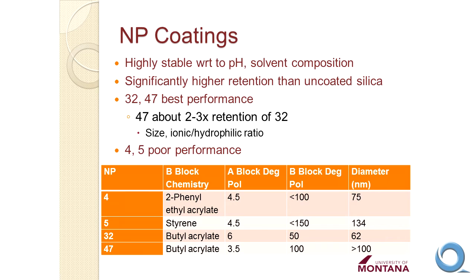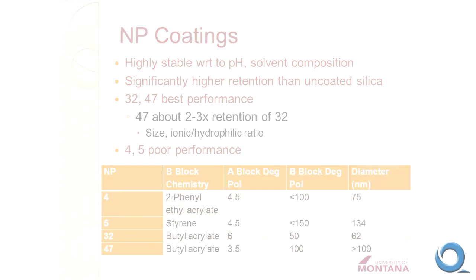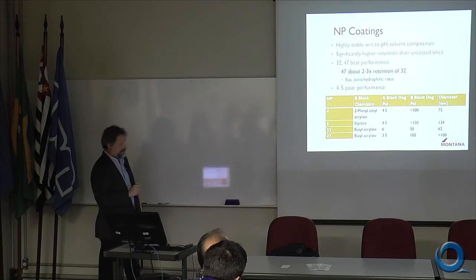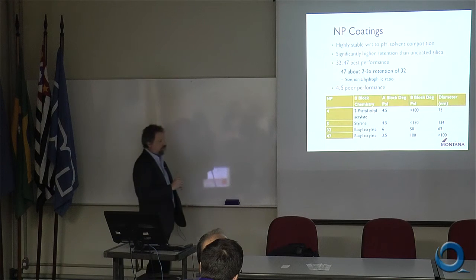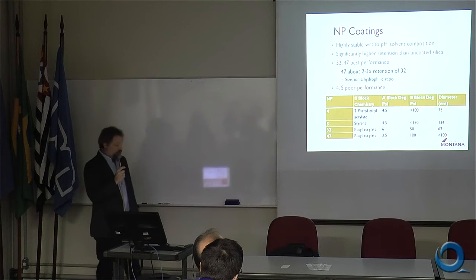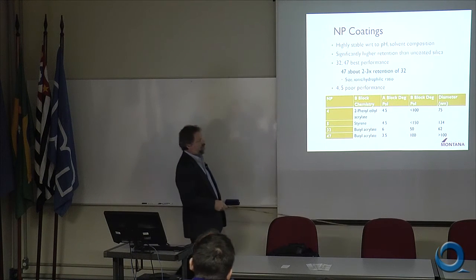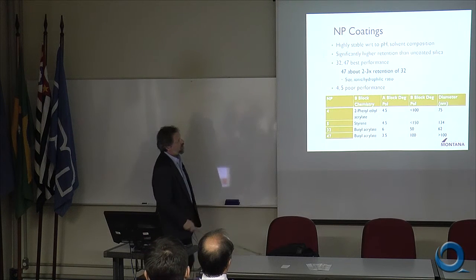All right. I mentioned that I came with a series of nanoparticles and that these are the ones that we used. First thing that we noticed in the first weeks of doing these experiments is that when we coat the silica with these nanoparticles, we get a very highly stable coating. We don't see changes in retention of analytes over time. We can reproduce our experiments over and over and over again. And in fact, we have one column which is coated with this nanoparticle number 47 that we've used since February, and we're still using it just a couple weeks ago, and we're still getting the same amount of retention. We've done probably 100 different injections on the system, and we've exposed it to lots of different solvents, high pH, low pH, and it remains a very stable modified surface.